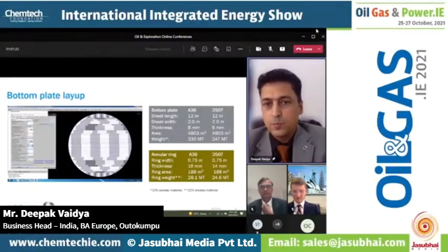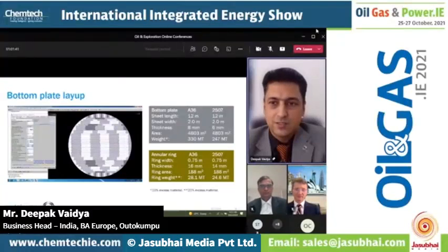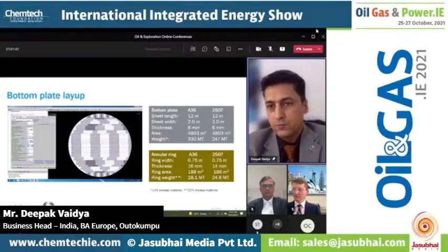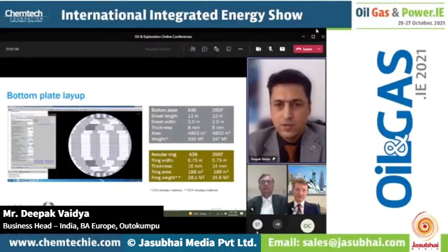So the weight for bottom plate in that 79.5 meter tank is 330 metric tons when you use A36. When you use 2507, it is 247 tons. Along with the bottom plate, you have to change the annular ring also. The width is 0.75 meter, thickness is 16, and here we have recommended using 14 mm, area is 188 meter square, and same over there. The ring weight is 28.1 metric ton, and for 2507 it is 24.6 metric ton.